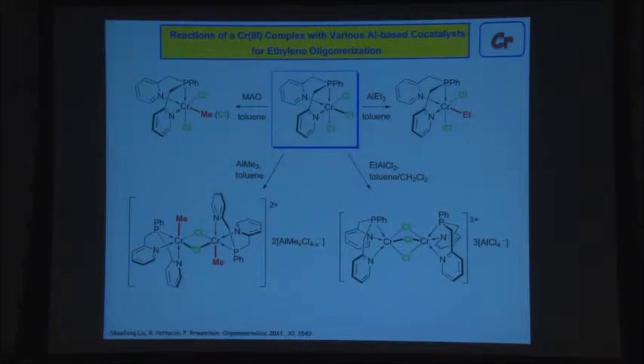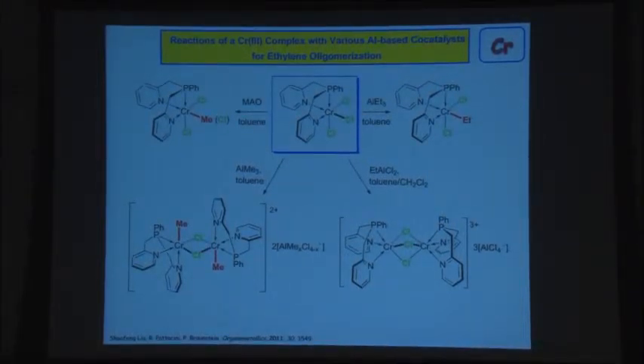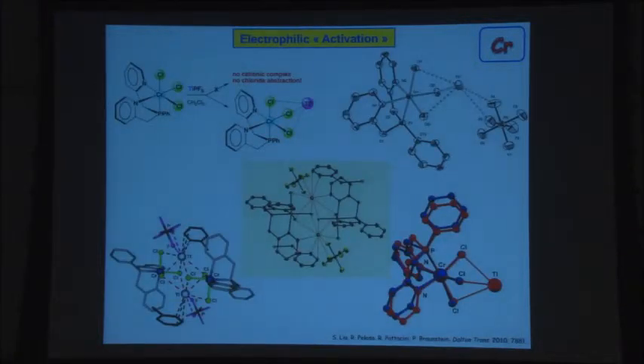So that's a way to trigger your curiosity. But I'm not claiming that these reactions are quantitative. It is very difficult to separate things from that reaction mixtures. Another way often to activate a metal center to make it positively charged is to remove the chloride. And typically, we use in inorganic chemistry chloride abstractors, which are very well known, that you may have used in your first year undergrad or maybe even in school to run experiments with silver nitrate to precipitate silver chloride, or thallium PF6, which precipitates thallium chloride, poorly soluble. This is a driving force for the reaction.